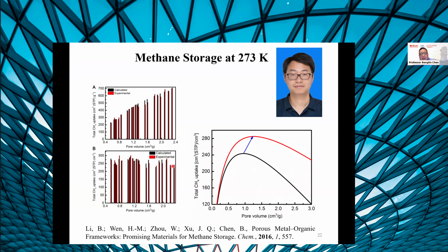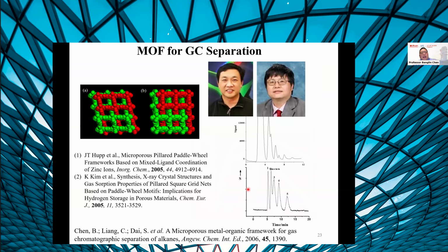You will see that at 65 bar and low temperature, this is presumably the maximum storage capacity and still below the Department of Energy's target. So we're wondering if we lower the temperature a little bit to 0 degrees, then the uptake can be significantly improved to another level. And you will see adsorption, desorption is an exothermal process, and we still need to control the temperature. Okay, now we turn to the next part.